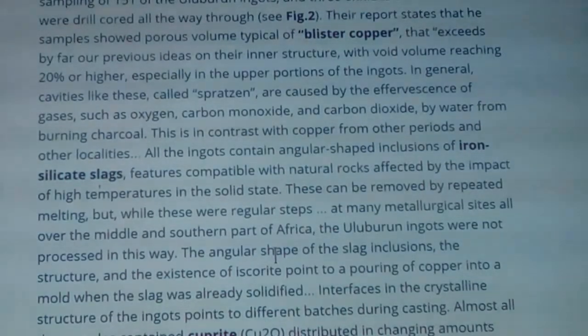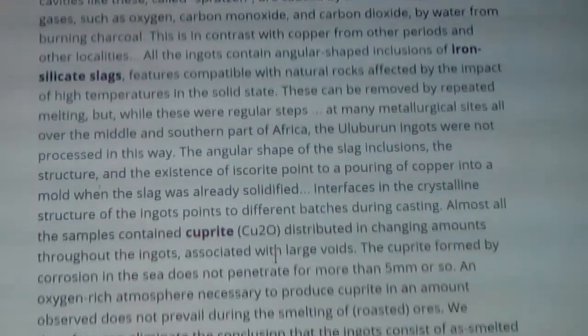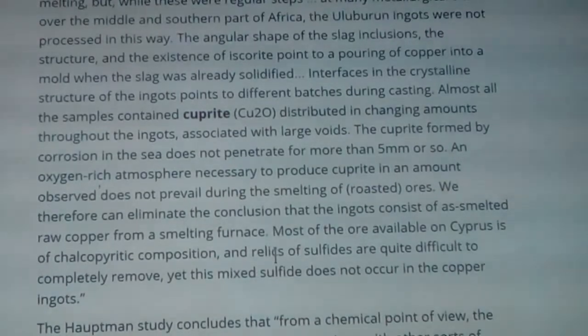These can be removed by repeated melting, but while these were regular steps at many metallurgical sites all over the middle and southern part of Africa. the Uluburun ingots were not processed in this way. The angular shape of the slag inclusions and the existence of iscorite point to pouring of copper into a mold when the slag was already solidified. Interfaces in the crystalline structure of the ingots point to different batches during casting.